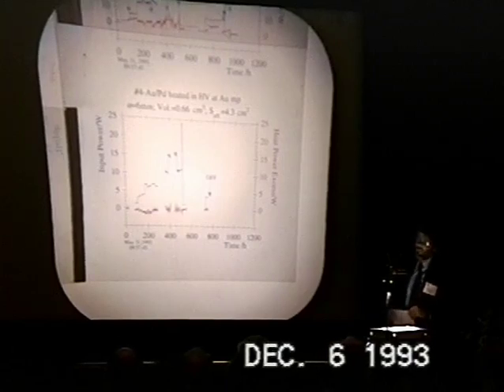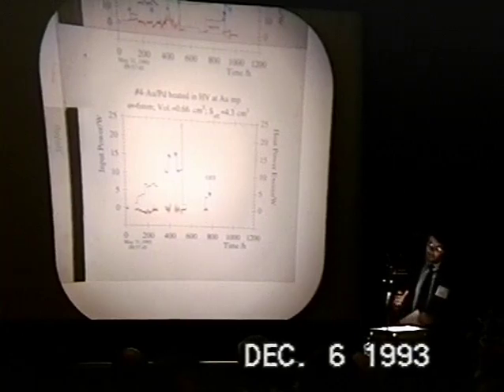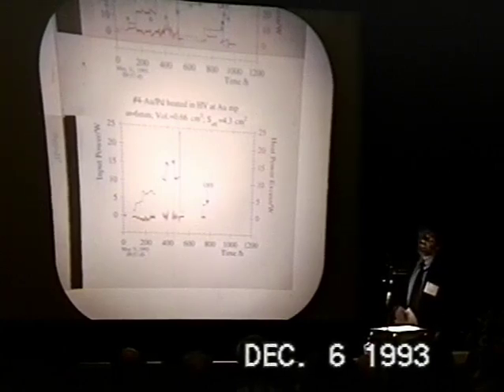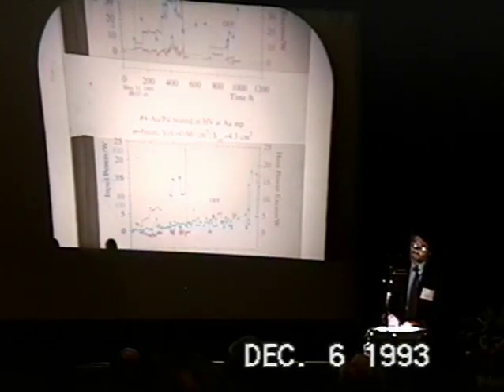This is cell number 4. This cell is constituted by a cathode of 6 mm diameter, and in this cell we didn't find any significant excess heat. I have to remind you that in our calorimetric measurement, the error is within 10%, and the detection limit of excess power is less than 1 watt. The helium-4 scale is different. In this cell, the helium-4 increases slowly, reaching about 300 ppb.